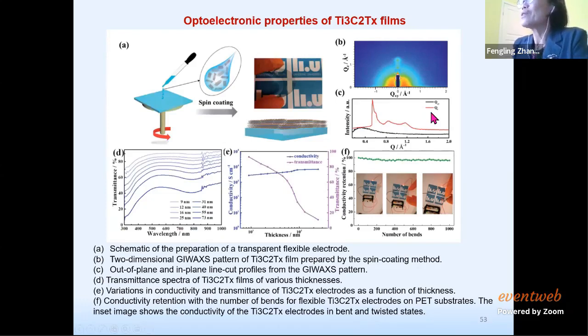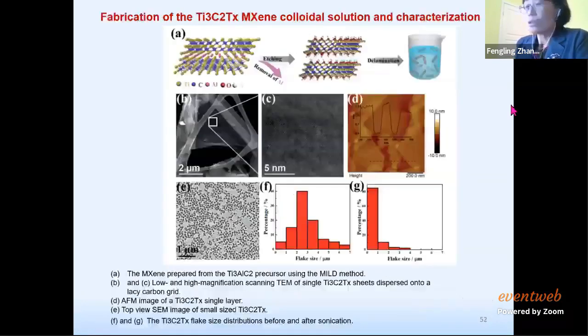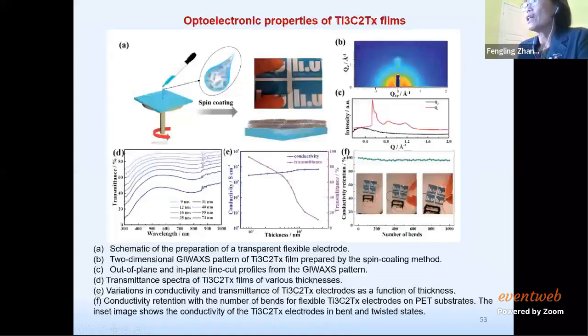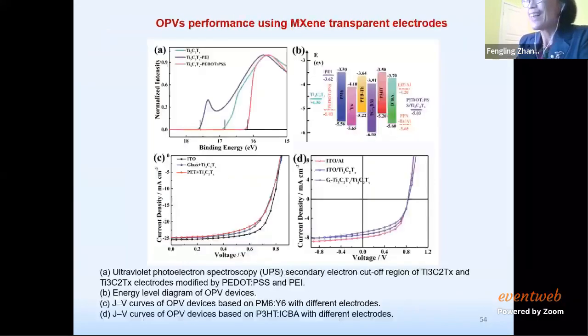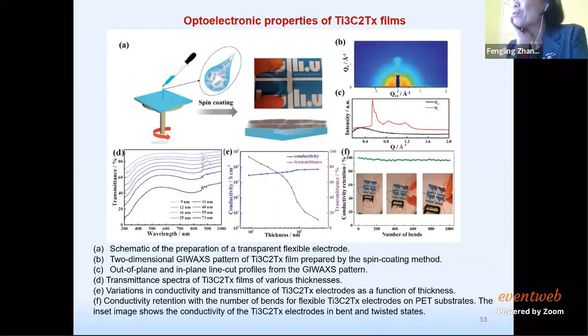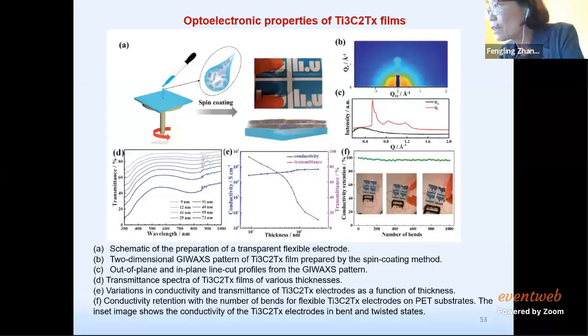The electronic properties of this film are still MXene, another kind of MXene. The transmittance will change with the stoichiometry. Here shows the optoelectronic property of this film, and then we make a device. We also show the conductivity. When we bend it, sometimes the material may crack, and then the conductivity will decrease. In this test we checked, and you can see the conductivity stays quite good, even when we bend it many times and at different angles.